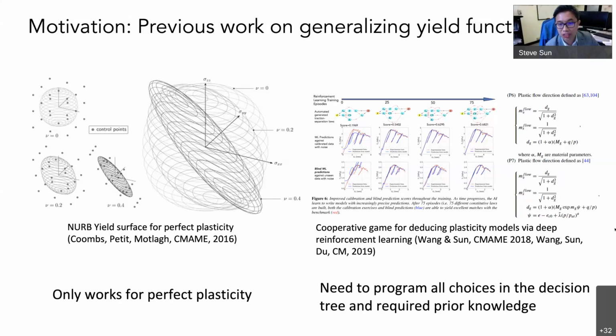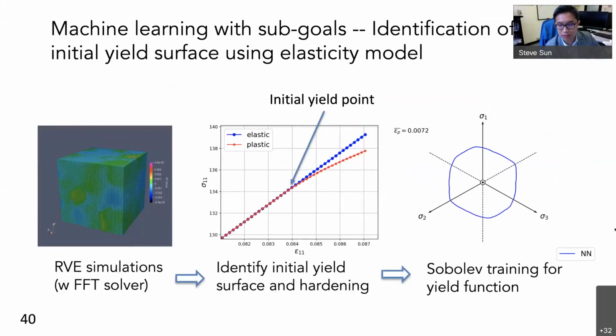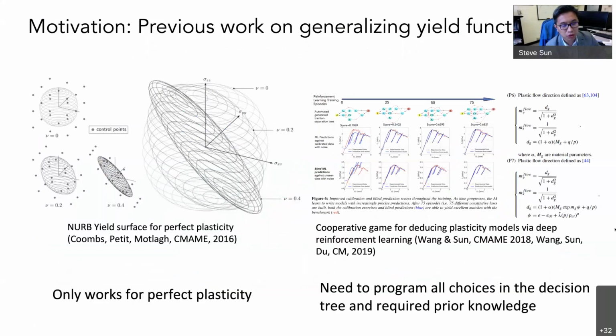We simply want to evolve a level set in the parametric space. In this case, for isotropic material, that would be just the principal stress. So with direct numerical simulations, we can run simulations that are purely elastic and then compare them with the DNS that activates the plasticity portions. And from that, we can obtain the data that identify the plastic strain, and from that, we can constitute a yield surface. So there is previous work on using NURBS to identify the yield surface for perfect plasticity.